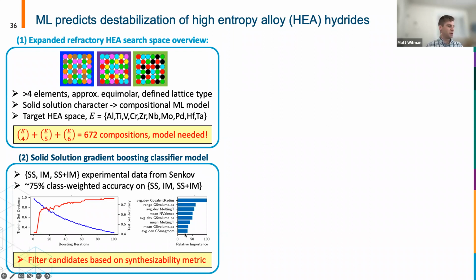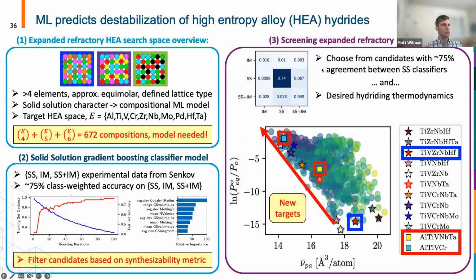Interestingly, if you do the interpretability analysis, this model is basically just the Hume-Rothery rules with a few other features thrown in. So we can go ahead and screen our entire space. We choose, again, materials that are predicted to form this solid solution. And then here's the prediction of the equilibrium plateau pressures for all materials.